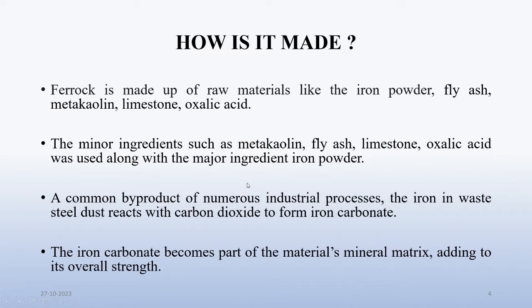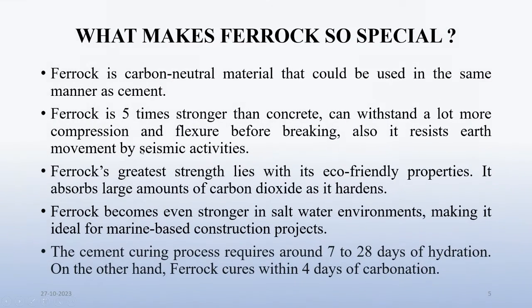Ferrock is made up of raw materials including iron powder, fly ash, metakaolin, limestone, and oxalic acid. The minor ingredients — metakaolin, fly ash, limestone, and oxalic acid — are used along with the major ingredient, iron powder. The iron powder in waste steel dust reacts with carbon dioxide to form iron carbonate, which becomes part of the material's mineral matrix, adding to its overall strength.